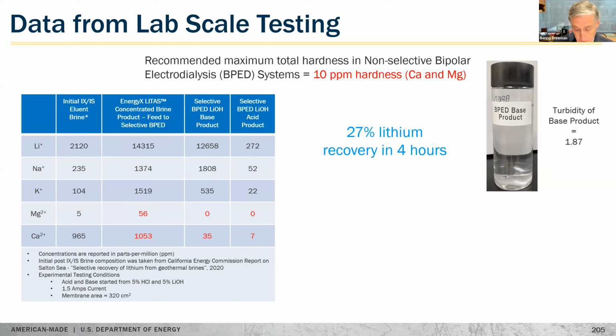And even with 1400 ppm of calcium and 40 ppm of magnesium, we have undetectable levels of calcium and magnesium in the base product. The membranes we're testing, even at lab scale, are at significant scale. We're testing about a third of a square meter at a time, and tests were started today that double that. So we're testing upwards of half a square meter, 6 tenths of a square meter of membrane.